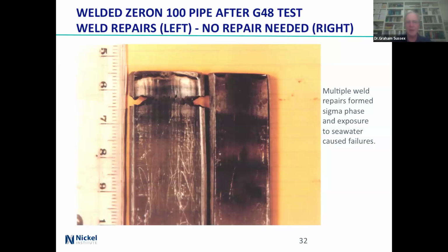This was an expensive thing. I've put in the name of the alloy, which is perhaps a bit unfair, but this was pieces of pipe. The contractors were a bit rough and ready. The bit on the left was welded and then weld repaired, and I gather in some cases weld repaired twice. And then they were put into seawater, and they wound up with corrosion, as in leaks, right next door to the weld. And that sort of thing happened.